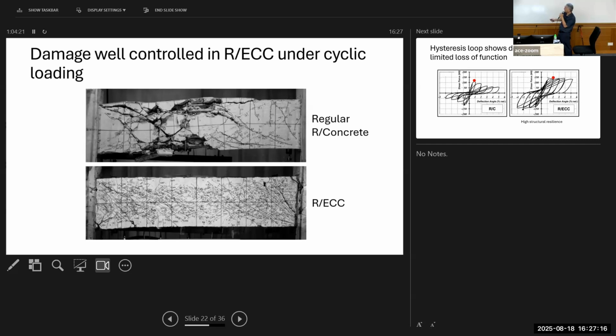You see the expected diagonal micro cracks. This diagonal because the load is fully reversed. So it's tension in one loading cycle and compression in the other. And then you form the other diagonal cracks. Same here, except that these cracks become very large in the case of the standard reinforced concrete beam, so large that you get spalling on the cover and exposure of the reinforcing bars. Okay, so this is not what you want.